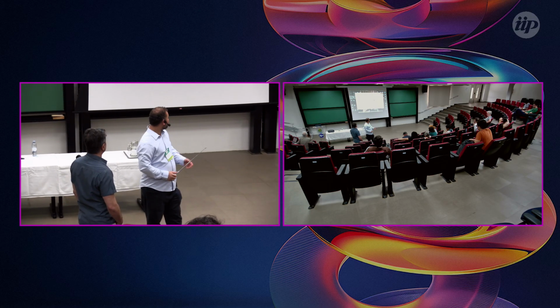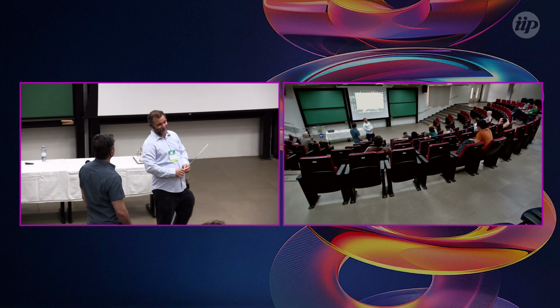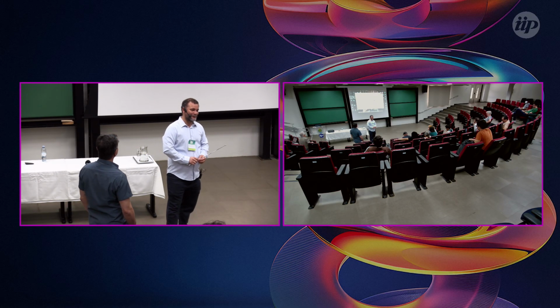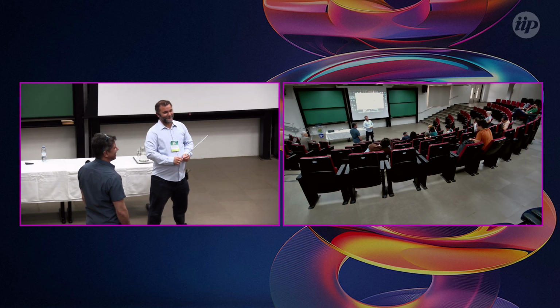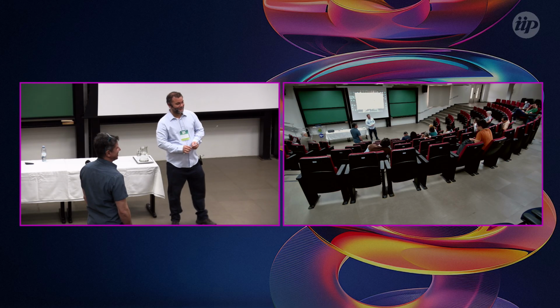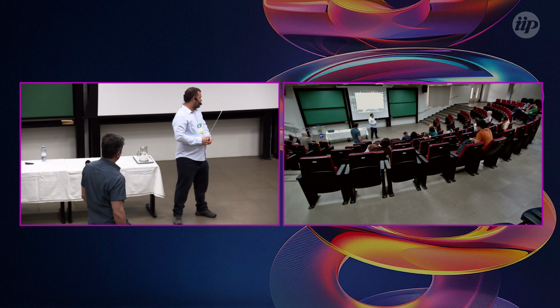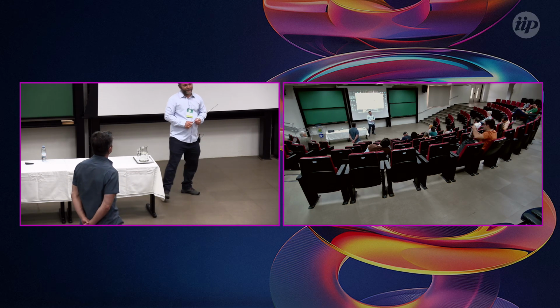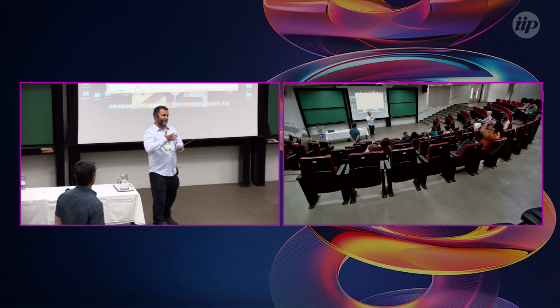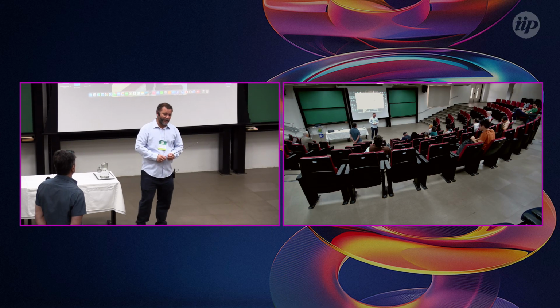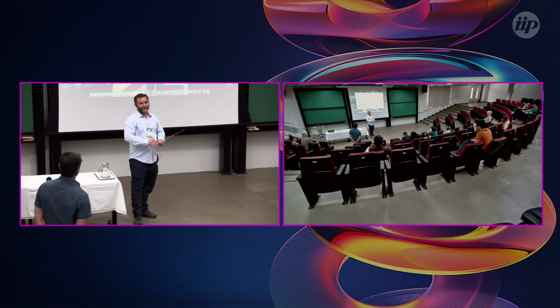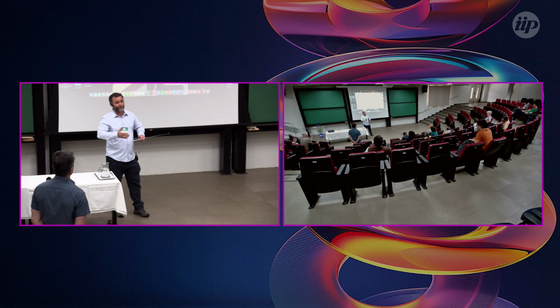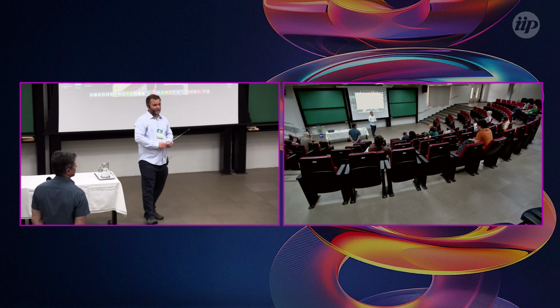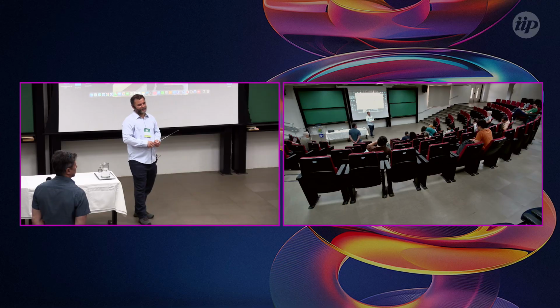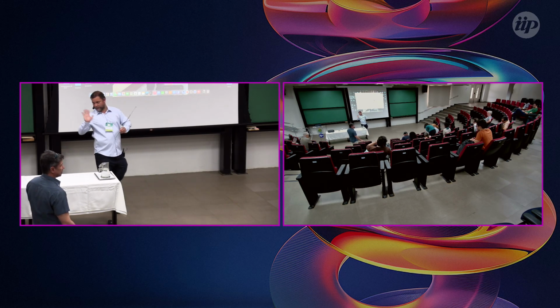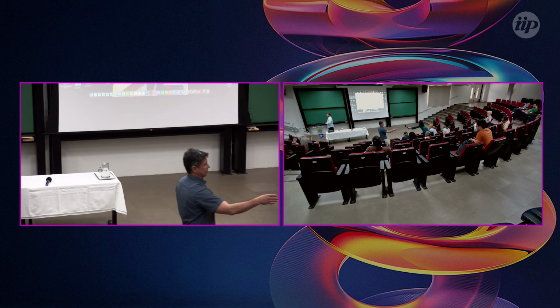I don't know. I think they should last long because one of the single photon sources is around, I believe, 200,000 euros. And if you buy a source for 200,000 euros, you expect that it will survive for a long time. There should be a correlation between the price and the lifetime. In general, I have to admit I never saw a real device from Quandela or SpareQuantum, but I believe it is kept in vacuum all the time. But in general, they encapsulate this kind of quantum dots. And as far as I know, when you have a thick layer on top of these quantum dots, it can survive for a few years. At least the gallium arsenide samples that I measured, the samples that I was growing, I was checking samples 7 years old and they were completely fine. And they were in air, not in vacuum.